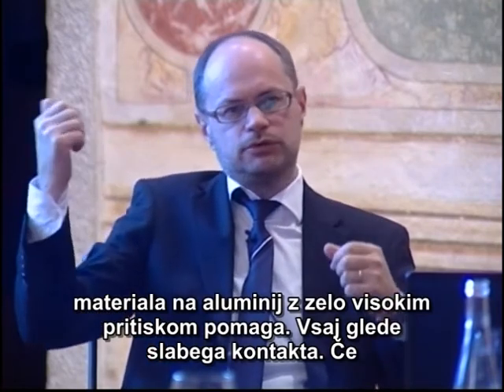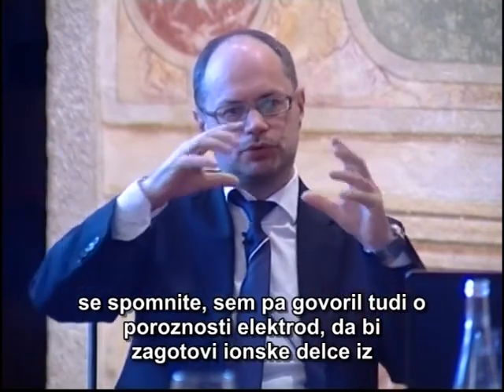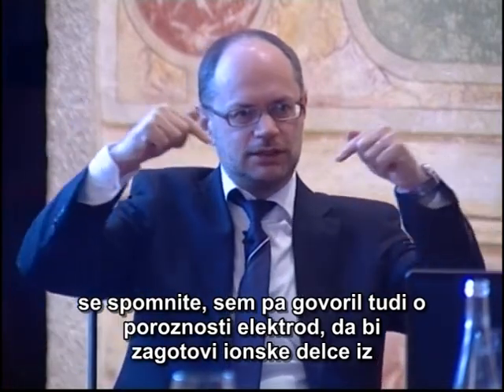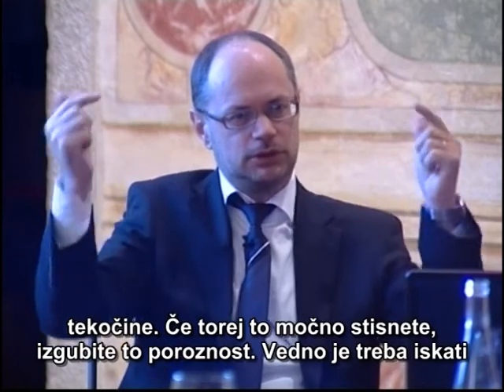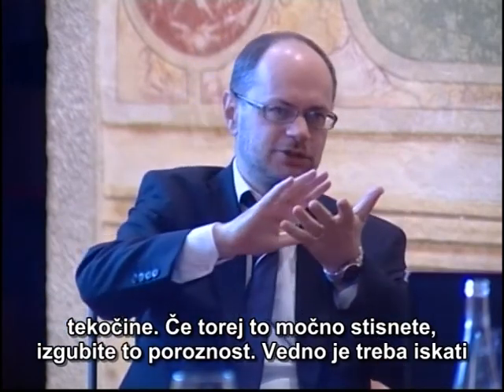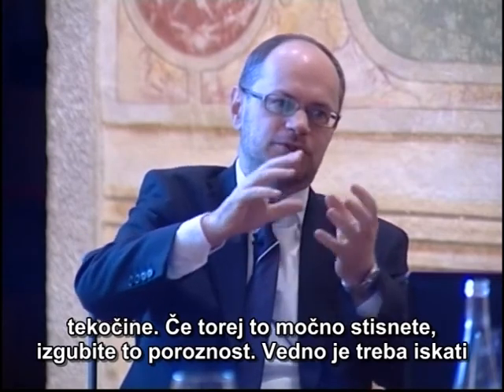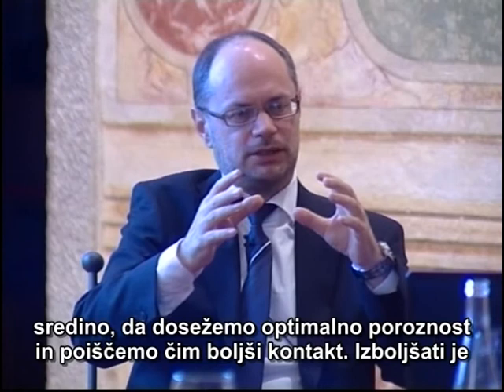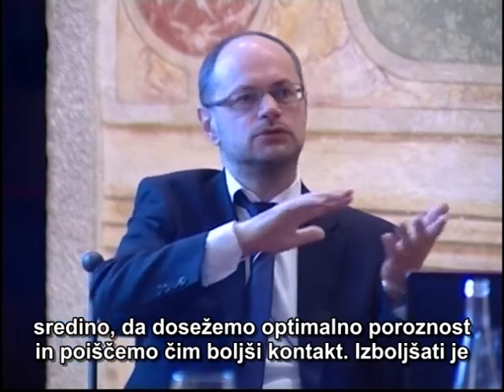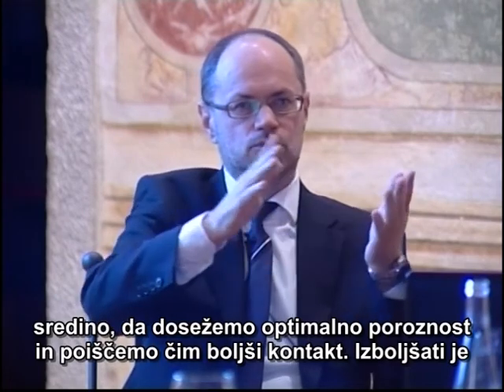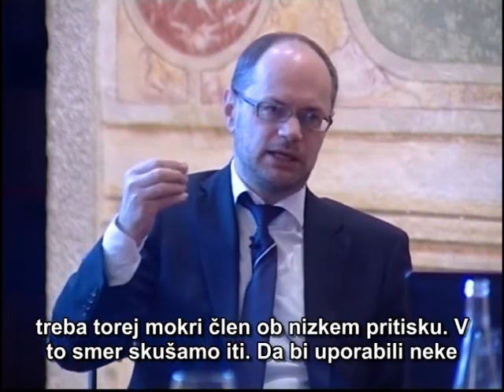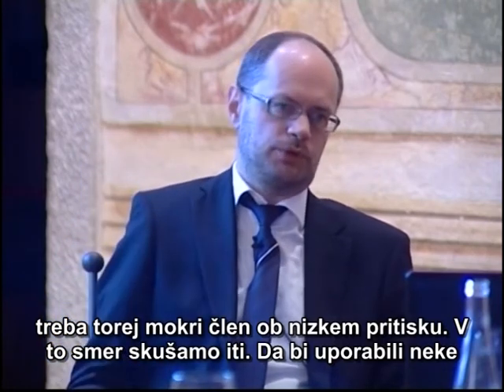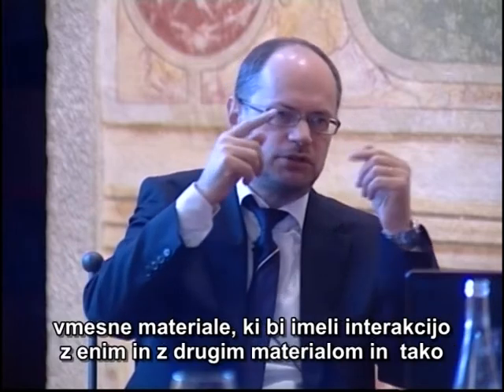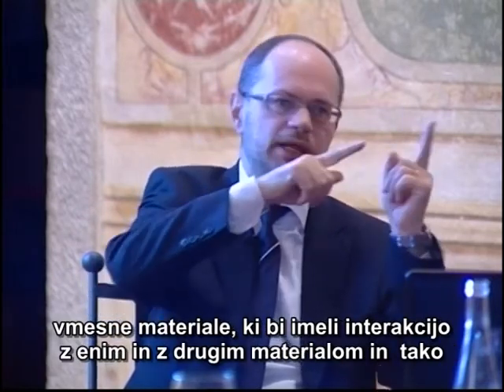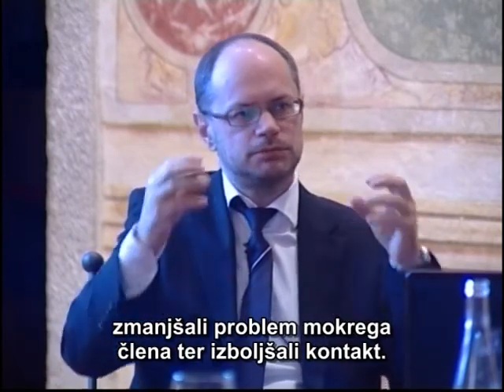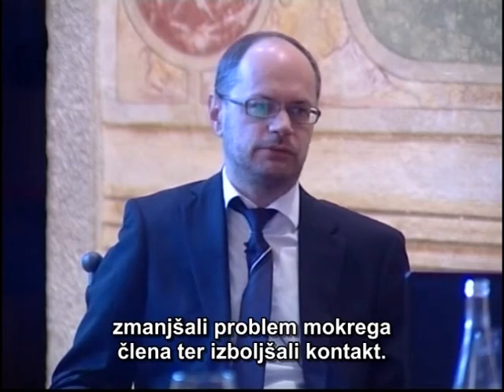But on the other hand, if you remember, I also was talking about the porosity of your electrode to provide ionic paths from the liquid. So now if you compress it, you lose this porosity. So there is always an interplay: to optimize the porosity, and on the other hand, to optimize this geometrical contact. So what you need is to improve somehow the wetting at low pressures. This is the direction where we try to go, to use some interfacial materials which will interact with one and the other material and decrease the wetting problem so that you improve the geometrical contacting everywhere.